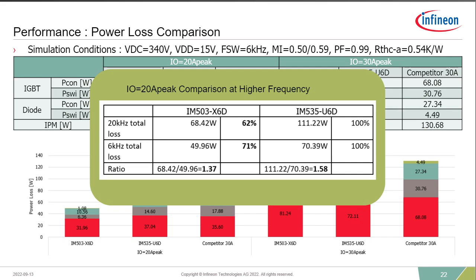And here you can see that there's essentially no penalty by going with silicon carbide by switching the frequency from 6 kilohertz to 20 kilohertz in the design. So you can essentially implement a 20 kilohertz switching frequency without having to change your thermal mitigation solution in your compressor drive. And so that's a major advantage for silicon carbide.